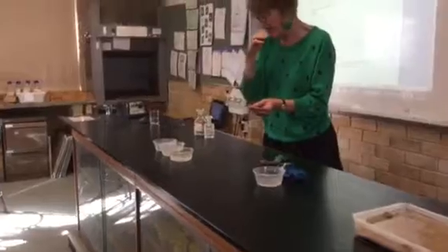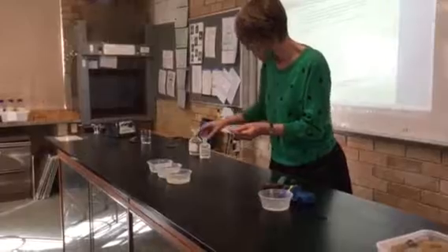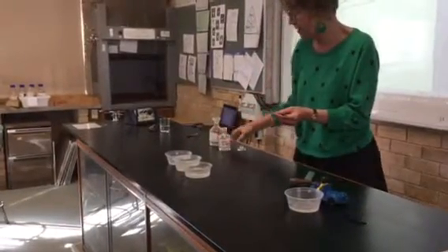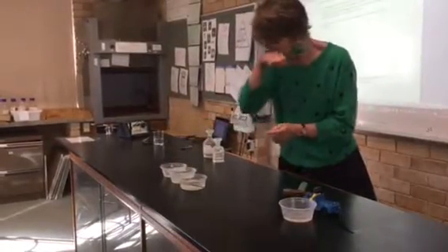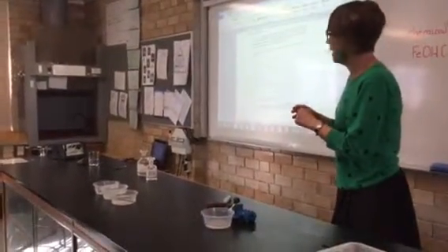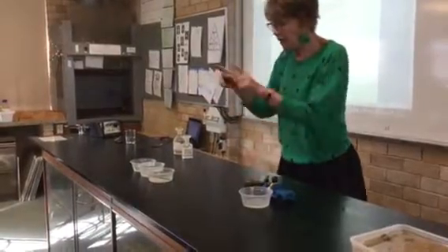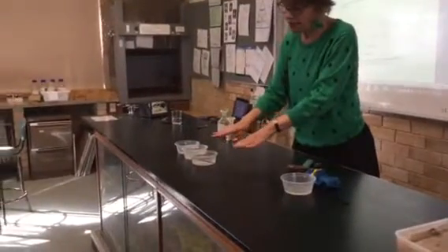So once we've removed what we can of the coral, we're going to go to our leaching water baths here, and because we know that our artefact is iron, we're going to just spike that water a little bit with some sodium hydroxide because we know that inhibits rusting, so we don't have the poor old cannon getting more rusted in the process of conserving it. Now, it'll sit in the water bath for really weeks, if not months, and we've got a process of diffusion happening. So say we had 100 units of chloride ion on that surface, then that first water bath would leave 50 on the cannon and 50 would go in the water.